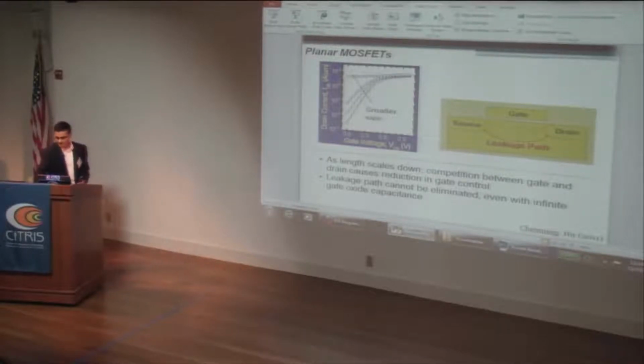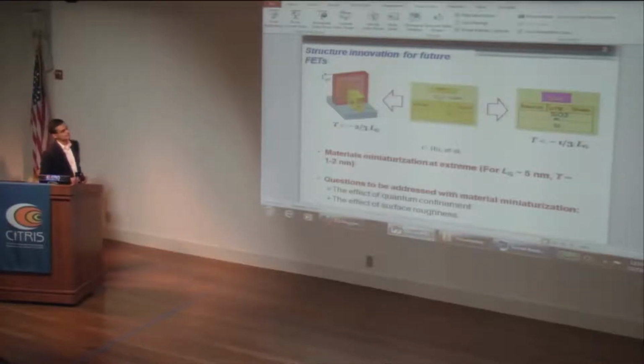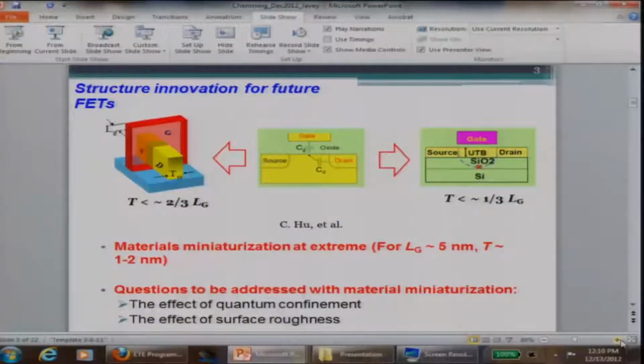So this is a common short channel effect that we have with conventional MOSFETs. And that was really the motivation for the work that was led by Chenming and colleagues here at Berkeley in the 90s to really solve this problem for scaled devices. So two different structures were proposed here at Berkeley, and one was, of course, the FinFET, which you heard about. And effectively, the idea here is that you have a very thin piece of silicon, a fin, and in this case, all of the body is close to the gate.